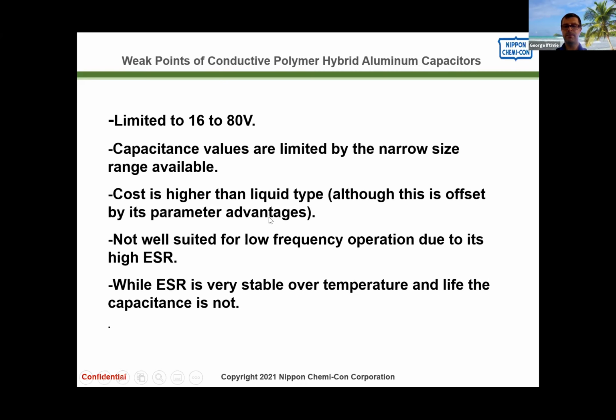Most common reason why customers switch from liquid parts to hybrid or polymers is because they're trying to decrease the number of capacitors used in a particular bank. So ripple current and ESR is typically the driving factor. And because hybrids or polymers have such a low ESR and such a high ripple current, the number of capacitors and the total capacitance also comes along with it. So there's really no need for a 2200 microfarad 18 millimeter by 40 millimeter hybrid capacitor, for example. At least not yet. But it is certainly possible from a manufacturing standpoint if that were to be the case.